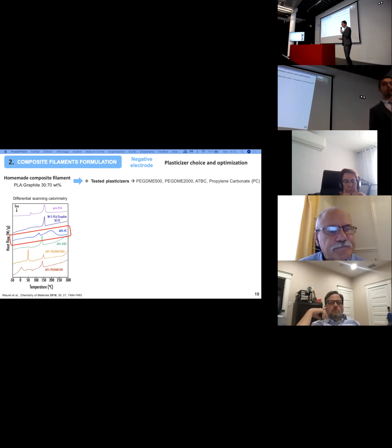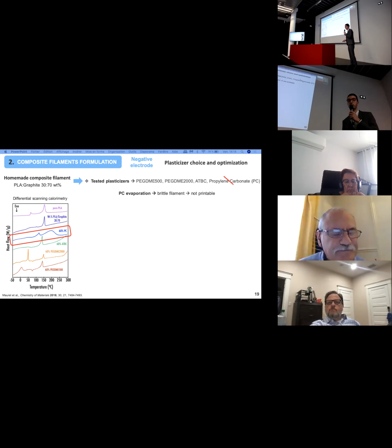Here, when we tried to make a filament with propylene carbonate, as you can see by differential scanning calorimetry, we have a broad endothermic peak between 120 degrees and 250 degrees, and it corresponds to the evaporation of this propylene carbonate. And thus, it corresponds exactly to our observation. The filament that we obtained was really brittle and so not printable. So here we ruled out propylene carbonate as a plasticizer.